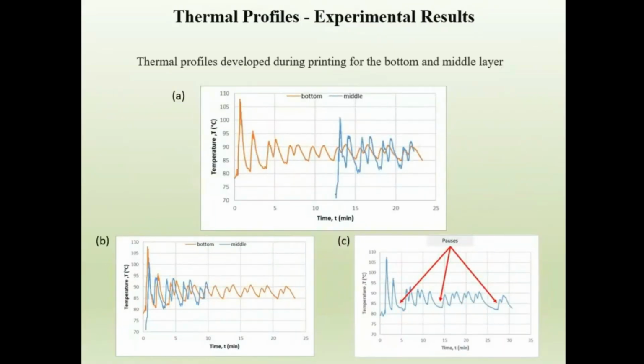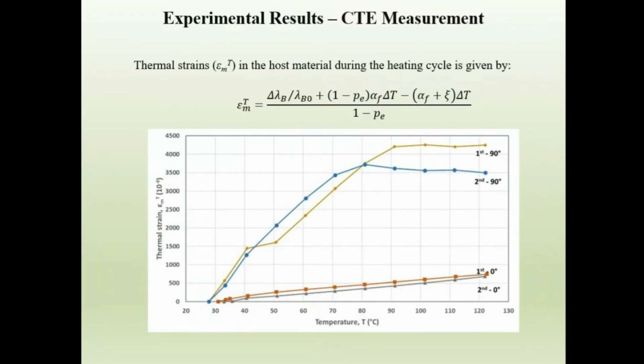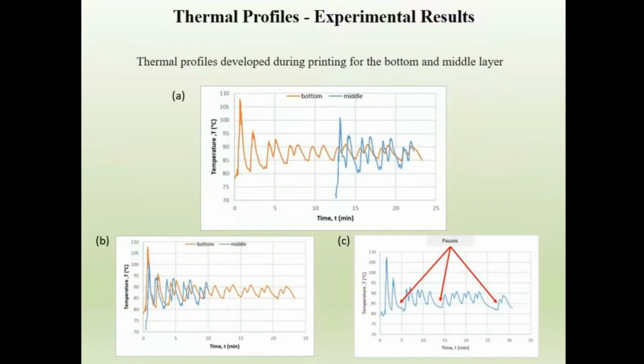So just to give you an idea of the thermal response, you can see what's interesting here. You can see that during the whole printing process, the material is experiencing temperatures that are quite above its Tg. For this kind of material, the Tg is close to 50-55 degrees Celsius. So we can see here the whole printing process. This is from the middle and above, so that's why we brought it to the left. You can see that they have similar thermal gradients developed during the process. But what's really interesting is that the material is printed way above its Tg during the whole printing process.